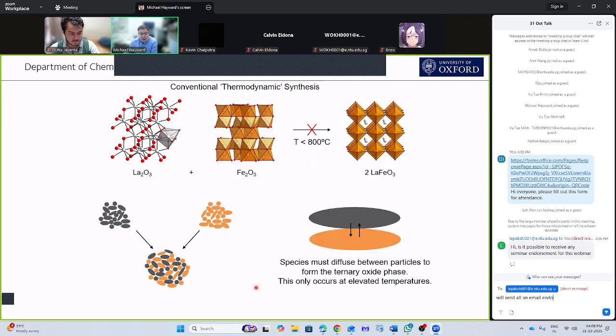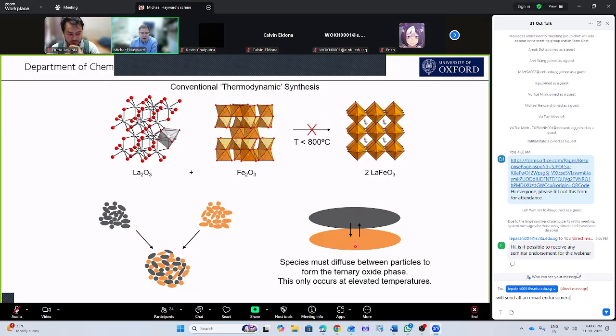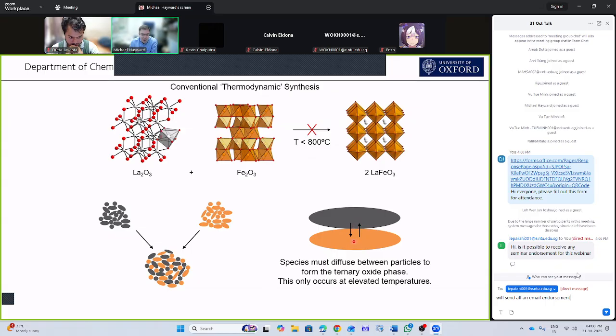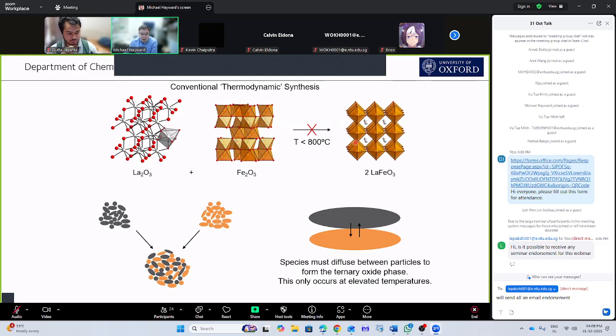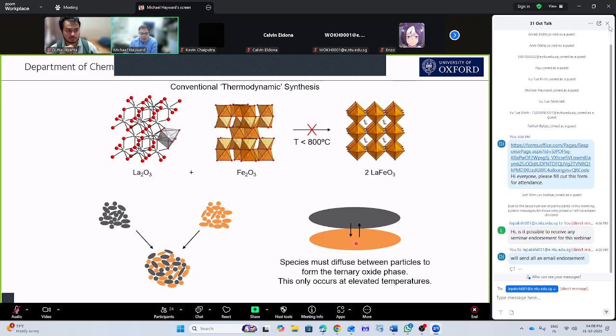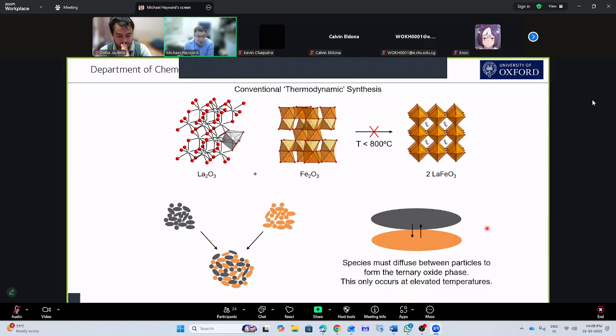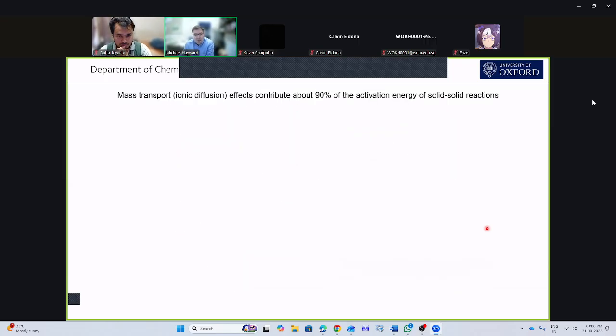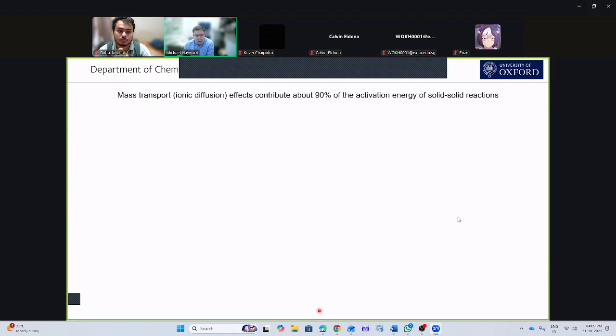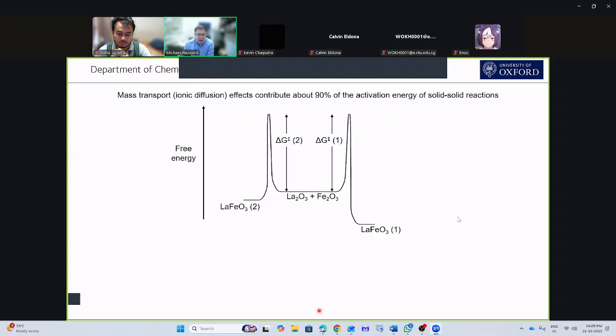And the reason for that is that I need my ions in my separate particles, maybe this orange one's iron oxide and the grey one's lanthanum oxide. I need the particles to diffuse, the ions to diffuse between the particles to make the ternary phase. And what we find is that the barriers to diffusion in the solid state, particularly for oxides, are very high. And in fact, what we can see is that these barriers to diffusion, what we call the mass transport contributions, contribute at least 90% of the activation energy in solid-solid reactions of oxides. And what that means is we could have an energy reaction diagram that looks a little bit like this. So I'm plotting the free energy of the system vertically, and then the reaction progress horizontally.